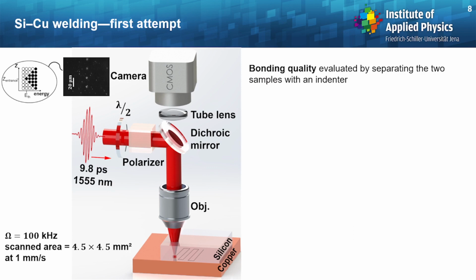Well, to do so, we'll employ the setup depicted here, relying on around 10 picosecond pulses at 1.55 micron wavelength. At this wavelength, silicon is transparent. Then we attenuate the energy optically with a half-wave plate and a polarizer before the beam is focused at the interface between silicon and copper by means of an objective lens. This objective lens here is also part of a microscope working in reflection and in dark field, and it allows us to position the geometrical focus with respect to the input surface of silicon. And then after the laser processing, we evaluate the bonding quality by means of an indenter connected to a force gauge.